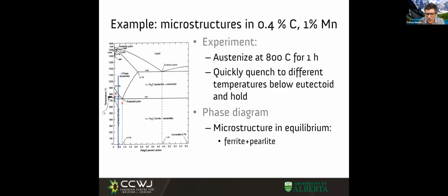Nobody calls it secondary ferrite, right? But it's definitely not the primary ferrite. It's a ferrite that is part of the pearlite. And pearlite is not a phase, it's a microstructure. Although fine pearlite looks all of the same color in an optical microscope, and sometimes you feel tempted to say, oh yeah, all this is a single phase. It's not, it's two phases that are closely intertwined.